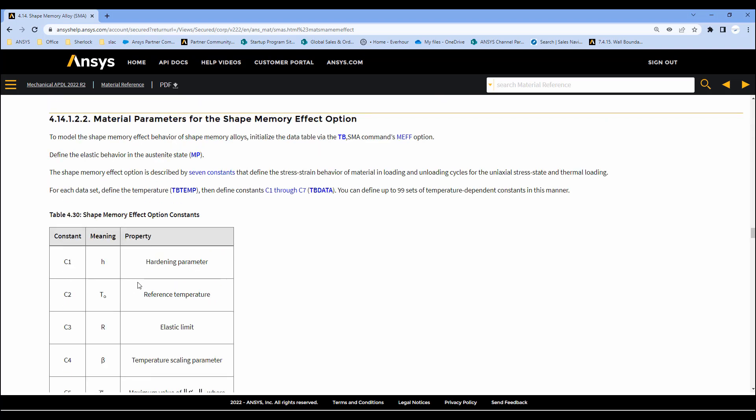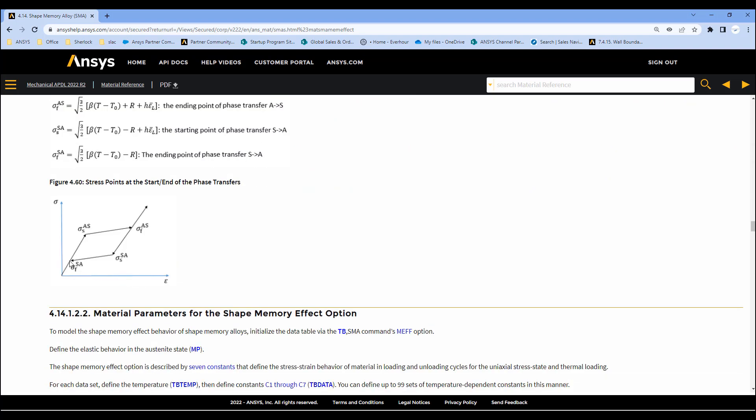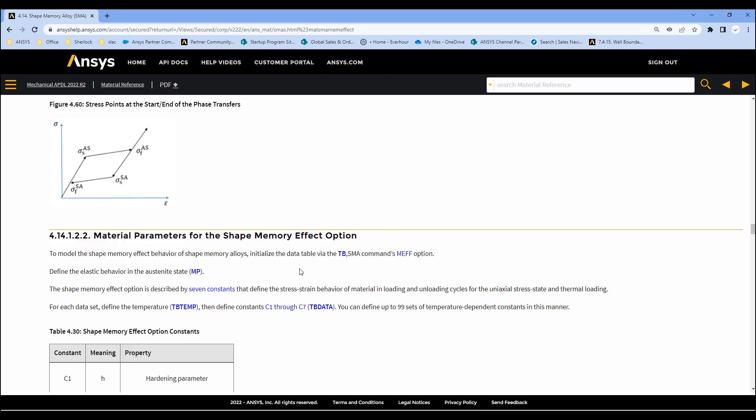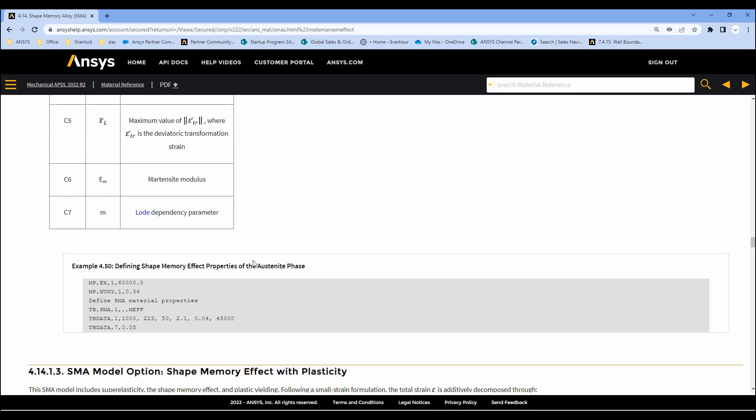One of the challenges for this is that it does assume that the transformation stress, the stiffness, when it transforms from austenite to martensite and reverse is the same. Now when people test these nitinol models out, sometimes you have different curves in different areas. So this is an assumption that's inherent in the shape memory effect. It does allow you to run large models much faster in the form of beam elements.